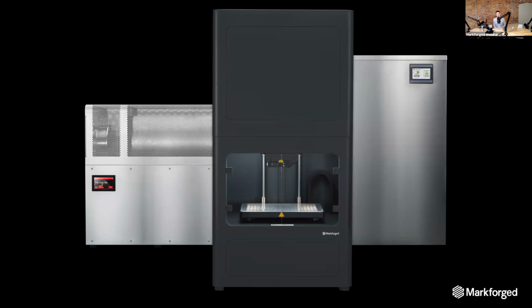The sintering oven then basically burns away the rest of the polymer, which escapes through those tiny channels that were opened up during the wash process. As it burns it away and heats up further, those channels shrink and disappear as the part becomes near fully dense, about 94% dense. As we reach the peak sintering temperature, which is about 85% of the melting temperature, the metal powder in there that was kind of next to each other becomes a full metal part. What you get out of that is a part that looks like this. The camera is probably showing it very small, but we can show a little more detail later. We have full metal parts.